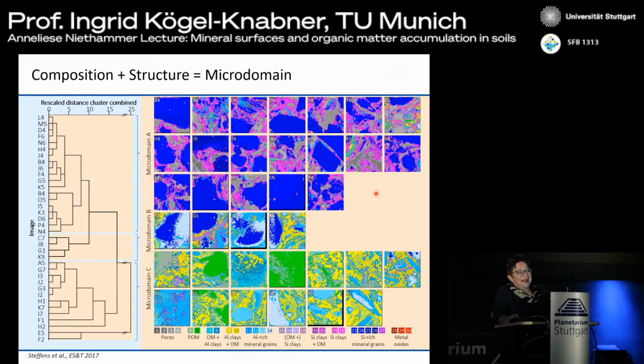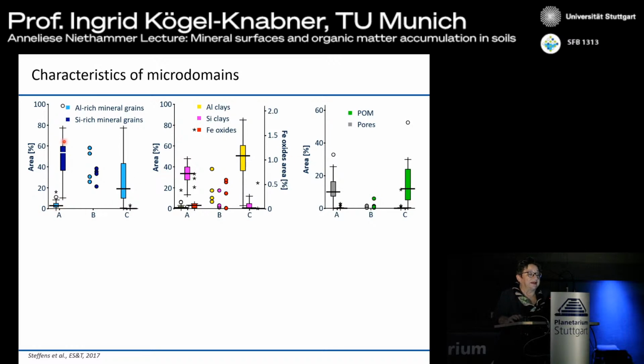But these materials are not. And if we make calculations, they are composed of two different types of materials. Basically, these large blue minerals are quartz or feldspar grains. When we do this in detail, we see that these Si-rich mineral grains are almost exclusively in the A domains, and the aluminum-rich mineral grains are in C. And Si-rich clays are in A, and aluminum-rich clays are in C. And the red is iron oxides.